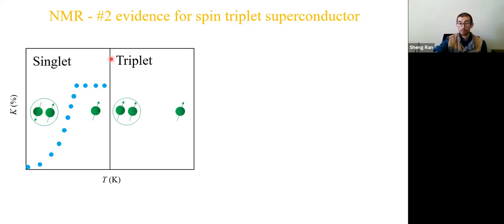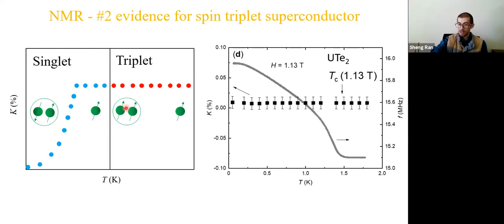But if you have a spin triplet pair, at high temperature you still have spin half electrons, but at lower temperature, at least along certain directions, two spins are parallel, giving you total spin 1. Two electrons give you total spin 1. So the total spin susceptibility is going to stay the same. This is what we found when we did NMR with the collaboration. So indeed, the NMR Knight shift stays constant over the entire temperature range.